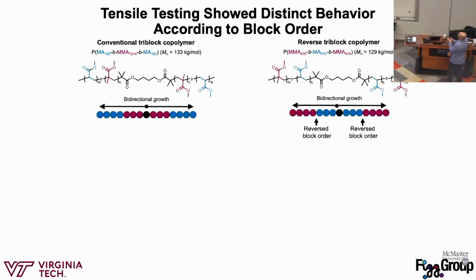So what we did is we made these block copolymers. This is a bifunctional RAFT agent where we have our methyl methacrylate on the inside and then our methyl acrylate on the outside. So this is going in a conventional blocking order. And then we used our chemistry to synthesize a block copolymer that has the same composition, so the same weight fraction of methyl methacrylate and methyl acrylate. The molecular weights are about the same, so they look chemically identical. The only difference is that we're flipping the order of the blocks using our chemistry.